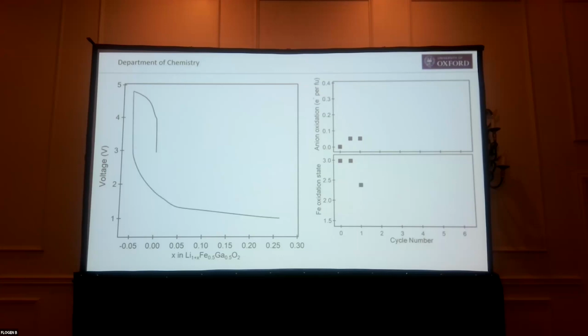In the discharge cycle, you can see it's vertical. We don't have any lithium in it, so we get below 3 volts. We take this as basically being limited, but we're not reducing the oxidized oxygen. That's the reverse. What we're doing now is reducing iron 3 to 2, so that takes us a little bit. We then do another charge cycle.